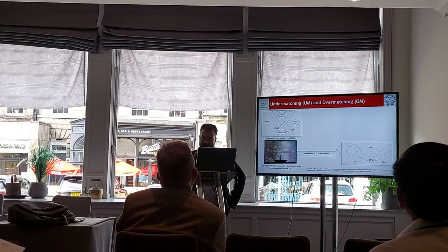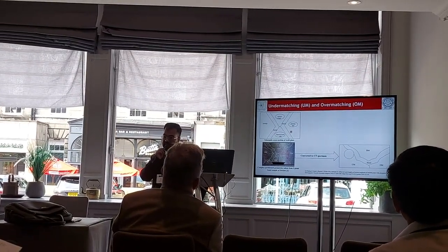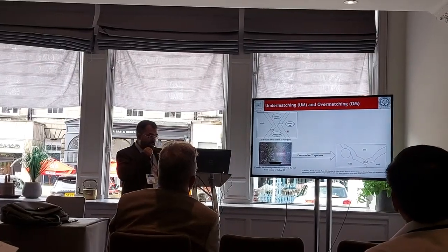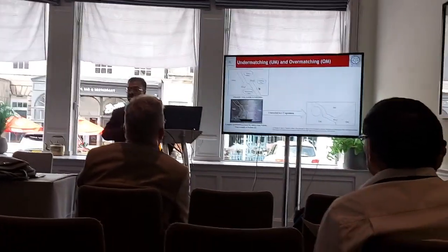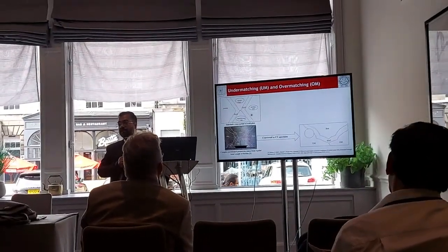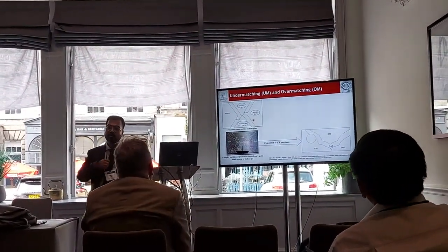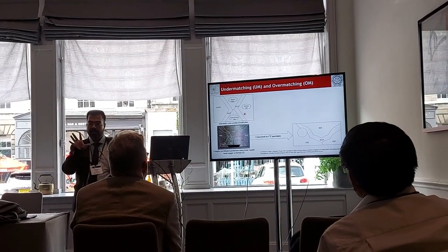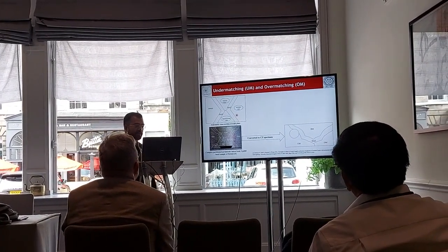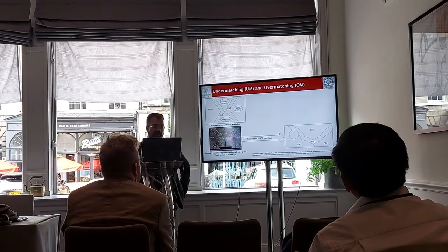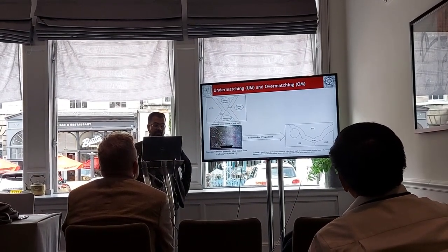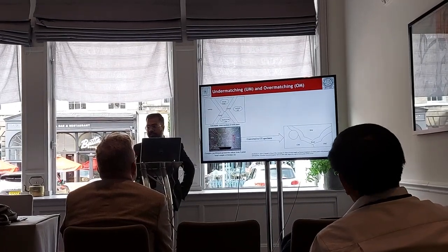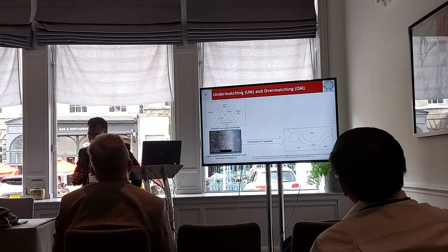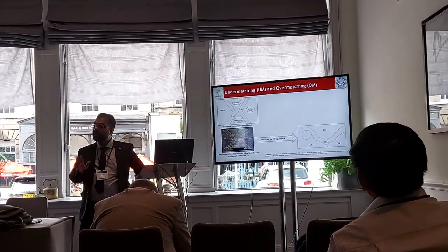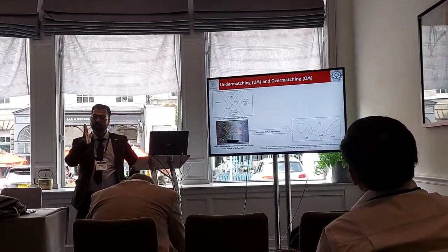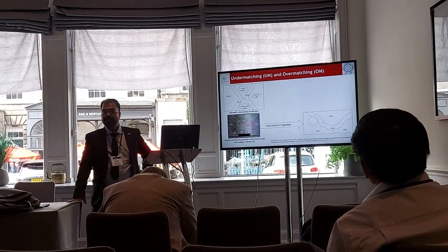But before that, there was already work done by Stefanik et al., and they did some experiments and numerical modeling on a 3-point bend specimen, and they used different filler materials to create overmatching and undermatching zones in the weld. This is not a dissimilar weld, but they have used different filler materials. So you have base metal, overmatching, undermatching, and then you have the heat affected zone. This is interesting because all the previous studies have been done on regular interfaces. So the interfaces were very smooth, vertical or oriented. But the real interfaces are not so.